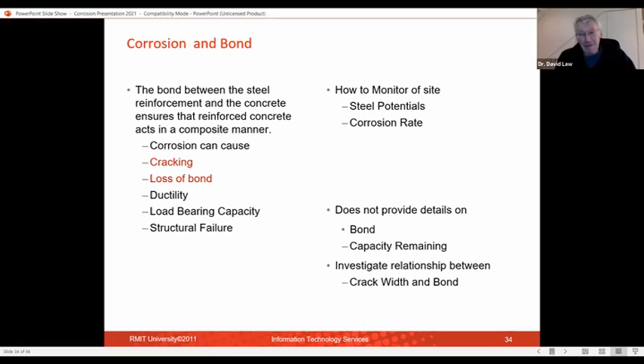So again, we're very interested in the bond of the steel, because obviously it's that composite action that gives strength to your structure and the capacity remaining. And we're interested in, is there a relationship between crack width and the bond? Can we see that we've got a relationship in crack width and bond? Because if we can monitor the cracks, then we might be able to understand how much bond we're actually losing as well, sort of within.